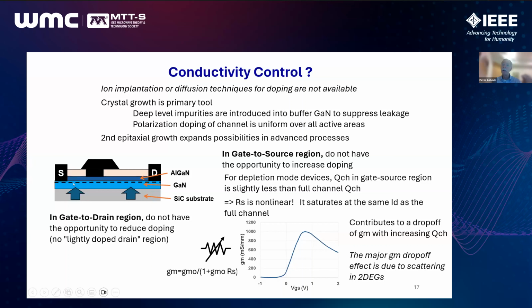Another issue is that the source to gate region forms basically the series resistance of the device. Of course, the channel charge is typically slightly lower than the channel charge in the gate. And in fact, the current saturates. It can add some degree of current limiting. So this is one of the factors that causes gallium nitride FETs to have a characteristic very rapid drop of gm as VGS increases. I should mention, and we'll be turning to later, that the major factor in the gm drop off is a different effect, scattering within the 2D gas.